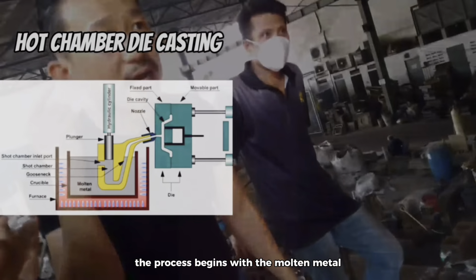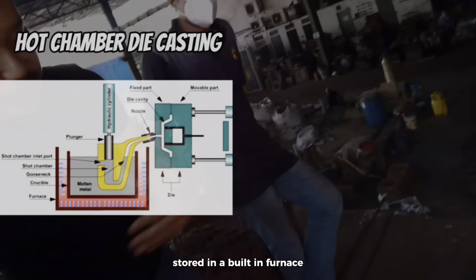The process begins with the molten metal stored in a built-in furnace. The metal flows into a gooseneck, a component that connects the furnace to the injection system. A hydraulic plunger then forces the molten metal through the gooseneck and the nozzle into the die cavity at a high pressure, typically between 700 and 5000 psi. This pressure is maintained until the metal fully solidifies. After solidification, the die opens and the final product is ejected using ejector pins. The die is then lubricated and closed for the next cycle.